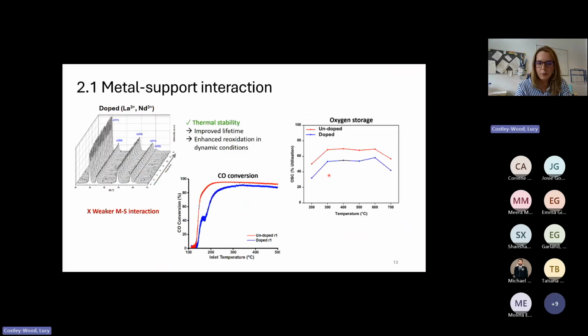However, the trade-off is that we're weakening our metal support interaction. And looking back to our oxygen storage and activity data, that weaker metal support interaction means that redox couple is not being as beneficial as it could be. So we're losing less oxygen from the material, and that corresponds directly to our conversion data because oxygen storage is really crucial for CO conversion when oxygen concentrations are low.